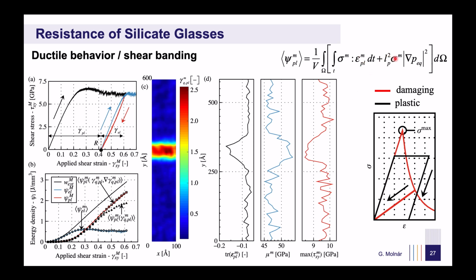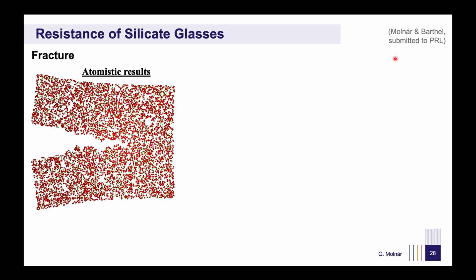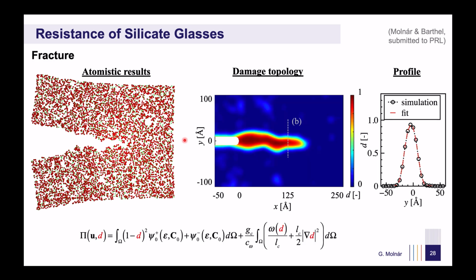Since we are primarily interested in brittle failure, we developed large-scale models to study crack initiation and propagation. One major challenge was identifying the precise location of the crack tip. As shown here, where only 5% of the sample's thickness is displayed, it is difficult to determine the exact crack position. To overcome this, we used the phase field model to fit stress, strain, and energy values obtained from the coarse-grained atomic model. This allowed us to identify a diffuse damage zone around the propagating crack.